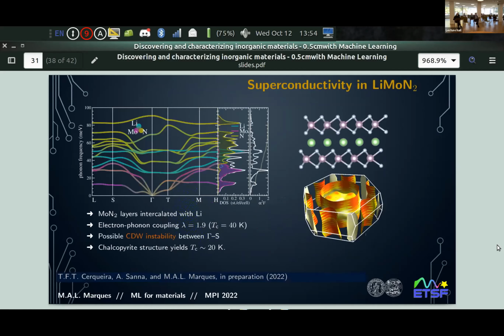So let's look at lithium molybdenum nitride just very quickly. This is the structure. These layers are isostructural to molybdenum diselenide or disulfide. So this is exactly the same structure. So you can get them just by replacing the sulfur by nitrogen. But it's exactly the same structure. And then it's intercalated with lithium. You can think about the structure like that.